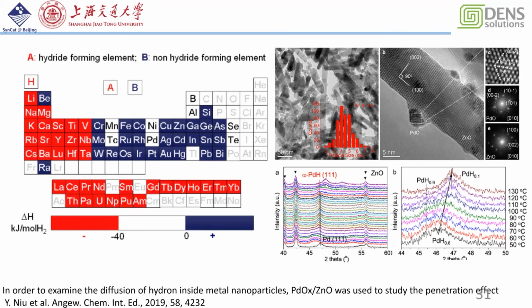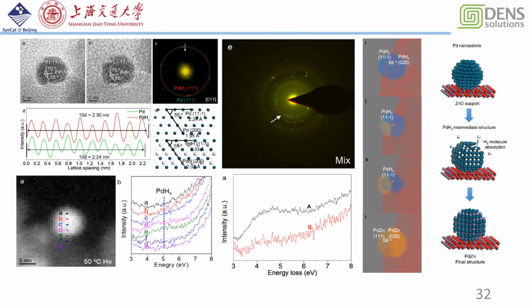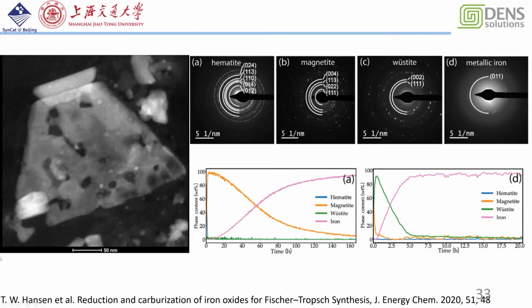So we somehow use palladium as a subject to study how the hydrogen penetrates into the metal and forms the metal hydride, because the palladium hydride is quite stable, so we can use different techniques to examine it. And in this paper, done by Professor Vincent Zhang, we use EELS and in-situ XRD technique to examine this, and found that really the hydrogen can penetrate into the palladium nanoparticle and form the hydride. This is the kind of evidence we can support our examination.